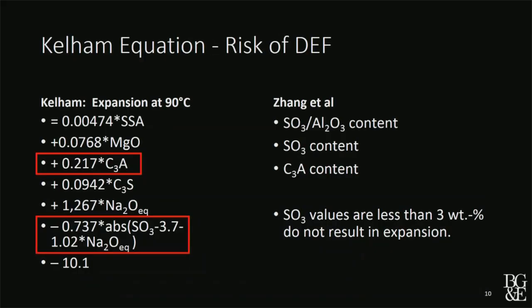So out of all the data that Kelham produced, he came up with an equation where he could relate the cement chemistry to whether it did or didn't expand. And he had a critical value that he came to, and he found that the C3A content, those rapid accelerating cements, which we use commonly in precast, were more susceptible to delayed ettringite formation. And those with certain sulfate and alkali contents were susceptible to delayed ettringite formation. So we did have a formula that helped us analyse some of the early cements 20 years ago.